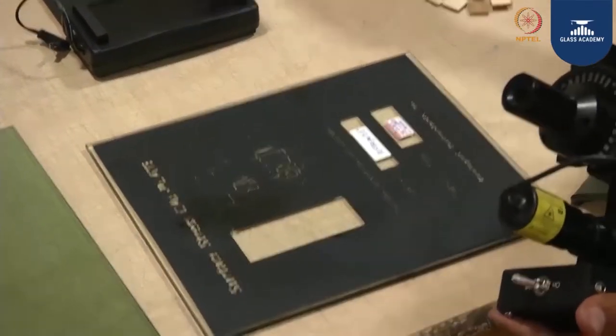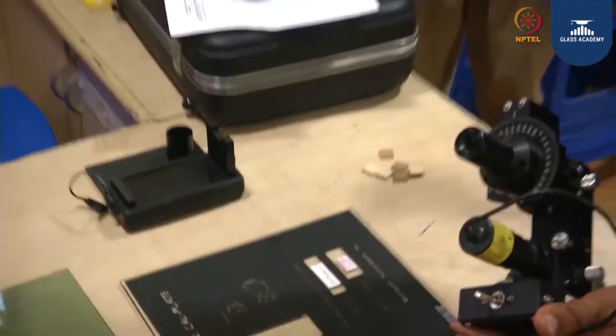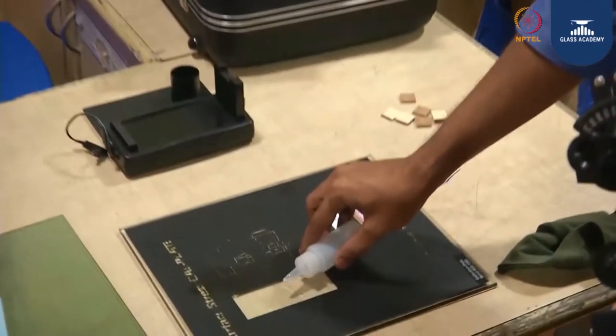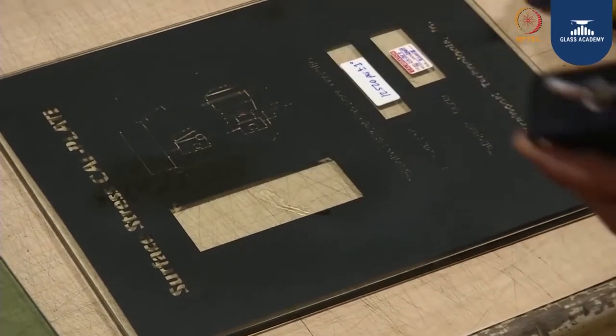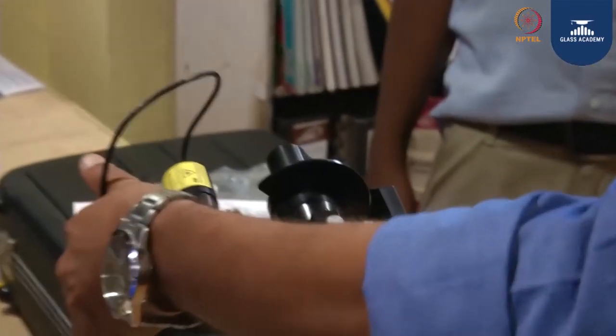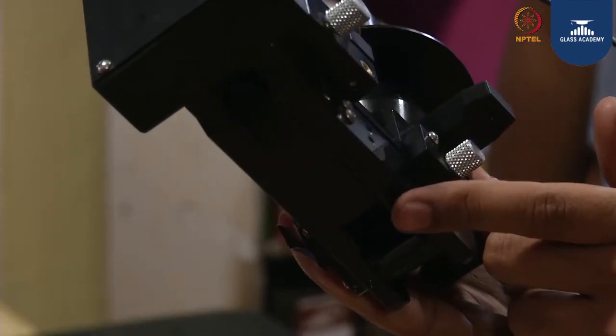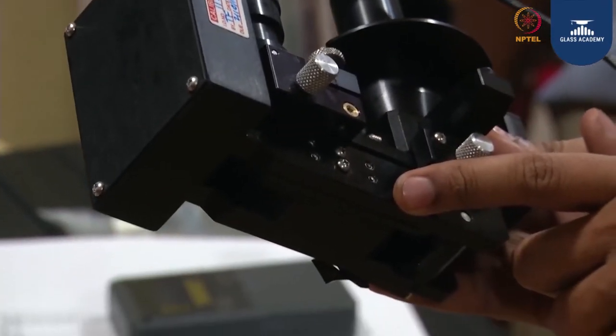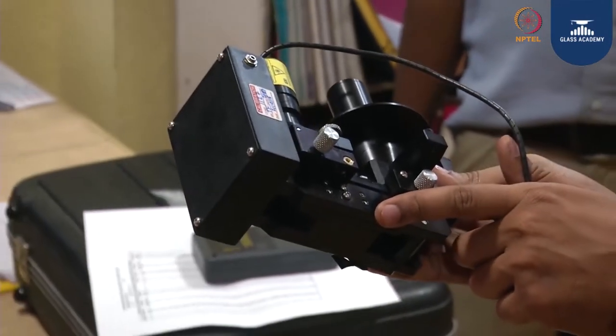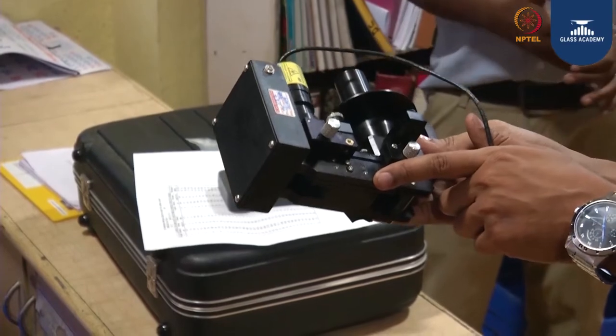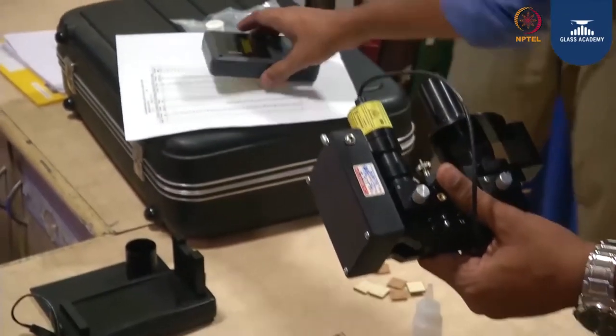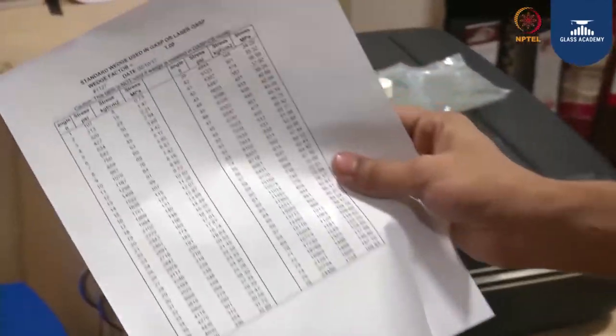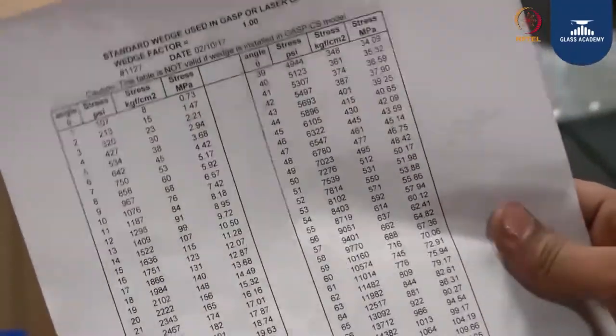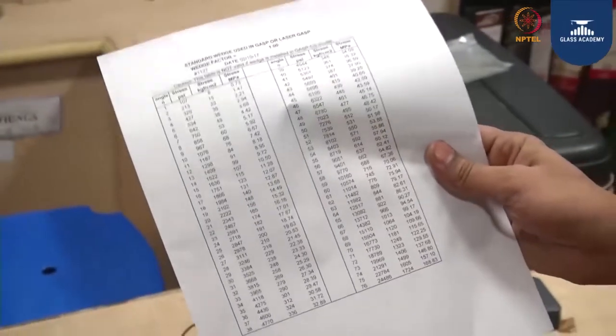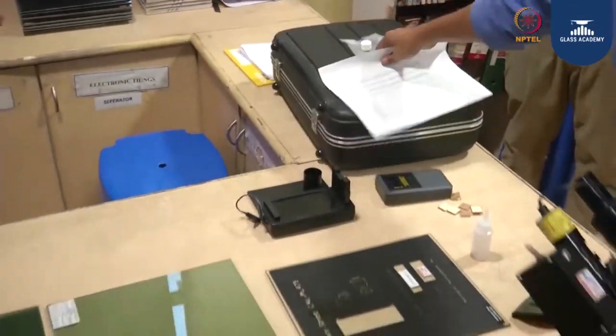This is known as liquid index. We need to place it on the area where we need to measure the reading. And inside, if you see, there is a prism at the bottom surface. This GASP works with the concept of light refraction. When the light passes through, it is reflected at a certain angle. Through that angle, we have one chart, known as the angle and stress reading chart. So based on the angle, we measure the stress induced inside the glass.